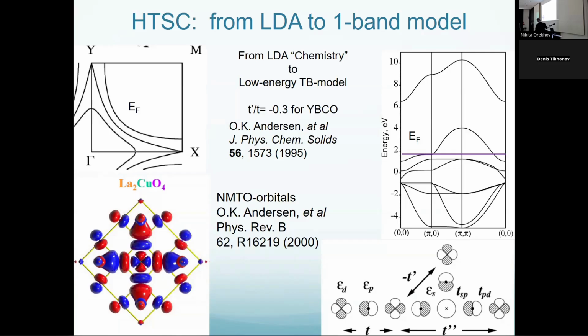But the Fermi level for metallic states crosses only one band, which is a combination of d states of copper and p states of all oxygen. So this is the wave function which corresponds to this valence band, which is important for superconductivity. It's only one band which crosses the Fermi surface. But chemistry or density functional theory said that there is an interesting effect. So you see this Van Hove singularity is pushed drastically down, not in the half of the band. This means that not only hopping, which is t, like here, but also this t prime is very important. And t prime is negative over t, and it's 30%.